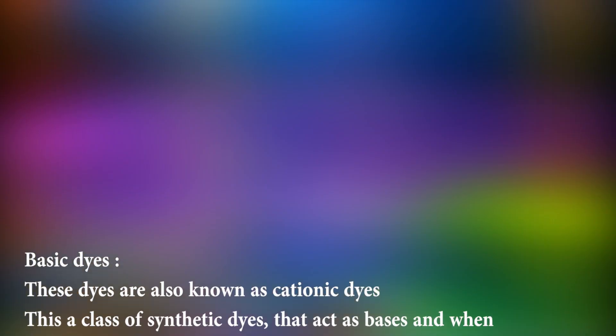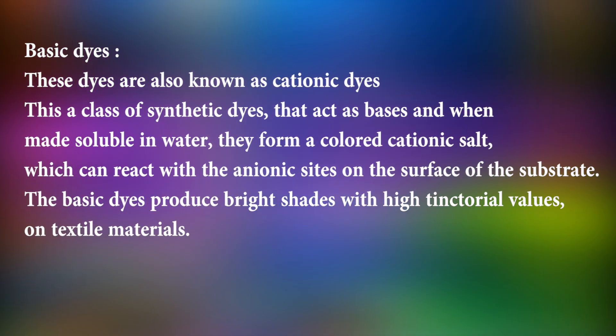Basic dyes are also known as cationic dyes. This is a class of synthetic dyes that act as bases, and when made soluble in water, they form a colored cationic salt which can react with the anionic sites on the surface of the substrate. The basic dyes produce bright shades with high tinctorial values on textile materials.